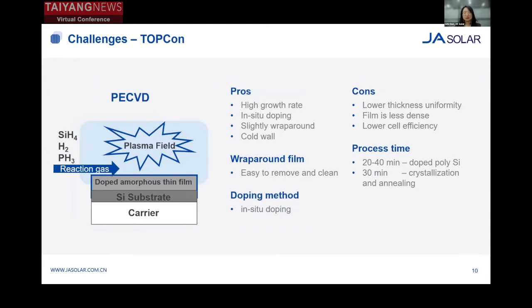Another way to fabricate TOPCon is PECVD. The wraparound film is light, so it is easy to remove and clean. The disadvantages are lower thickness uniformity, less dense film, and lower cell efficiency. The cell efficiency is now 0.05 to 0.1% lower than that made by LPCVD. So the main challenge here is to further optimize the process and achieve higher efficiency. And because of higher production capacity and low cost, more and more manufacturers choose this route.